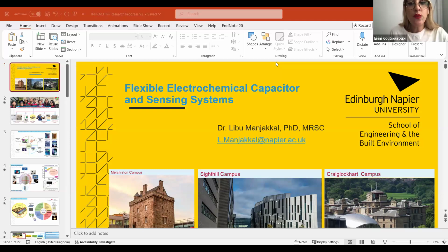And what is the repeatability of PEDOT:PSS based electrochemical sensors? Yeah, PEDOT:PSS, for example, is mainly used for supercapacitive ionic monitoring sensors, depending on the amount of electrolyte you are using. For example, if you are coating this material with a uniform coating, the mass loading is important for these electrochemical capacitors. In our approach, we use a drop coating or dip coating method. We have a controlled coating method, so our repeatability is with a variation of plus or minus 0.2 millifarad or something like that. We also measure 5 samples or so. Again, it depends on the amount of material you are coating on your electrodes.